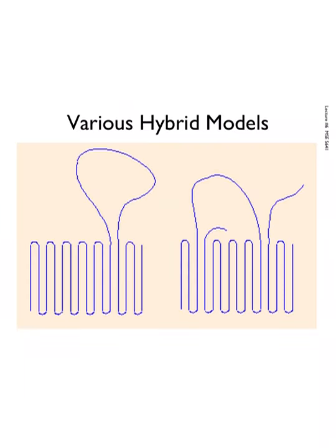And then there's a whole bunch of different versions of this, and people spend a lot of time thinking about this and trying to decide, well, how much of this and how much of that do we have? And even to this day, we don't really have a good way of quantifying this. I can tell you how much crystallinity there is in a plastic, but I can't tell you what the amorphous content is doing. I can't tell you what the shape of it is. I can't tell you whether it's neatly re-entering or undergoing this looping, or if it's going off, as it shows here, it could go off into infinity. We don't know. We don't have a good method for estimating that.